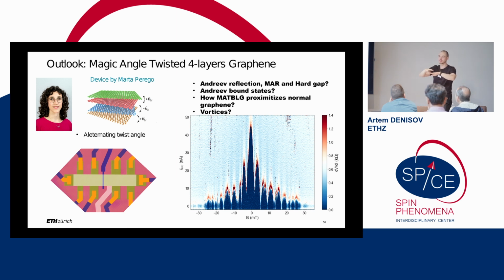They should be within a certain range theoretically to get a flat band. We didn't have enough devices to get statistics on how far off your angle can be, and with three angles we cannot measure them independently. But just looking at yield, 4 layers is easier than 2 layers. Surprisingly, it's more stable.